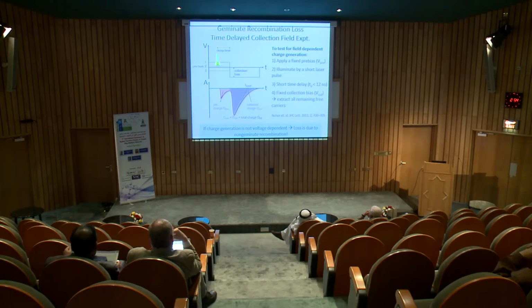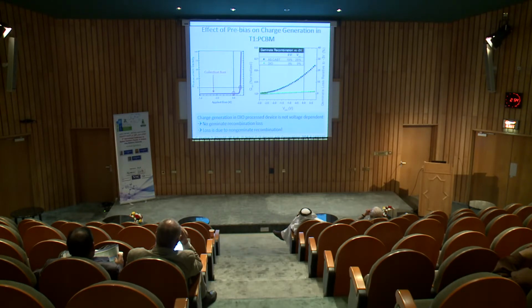This tells you whether the charge generation depends on the voltage or not. If the charge generation depends strongly on the voltage that you apply, it means the loss in your device is due to geminate recombination. If there is no voltage dependence, it means the loss is due to non-geminate recombination only. This is the type of data that we can collect by this method. On the right-hand side I plot the total charge generated by our device for the CAS and DIO processes, showing geminate loss relative to the maximum photocurrent generated in our device.